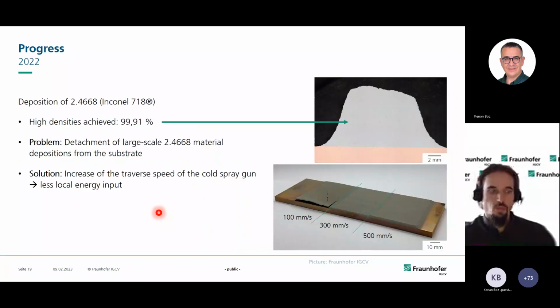Then furthermore, we wanted to also build Inconel or alloy 718 with cold spray. This is a rather tough task because of the high strength of Inconel 718, but we managed to get very high densities. This was actually quite a quick success we had there, but we had the problem that large material depositions of the alloy 718